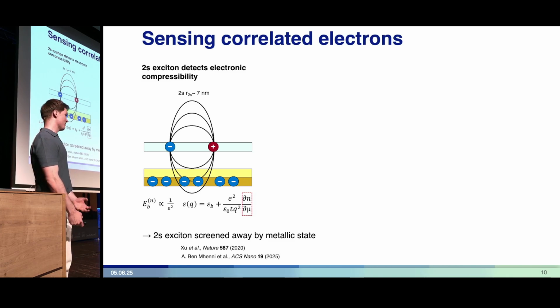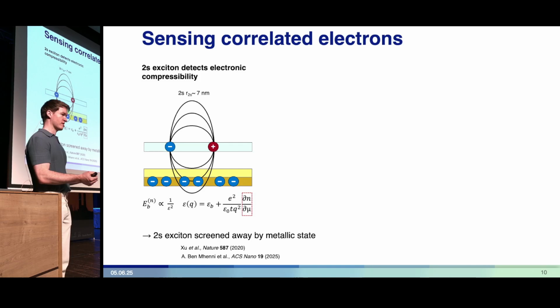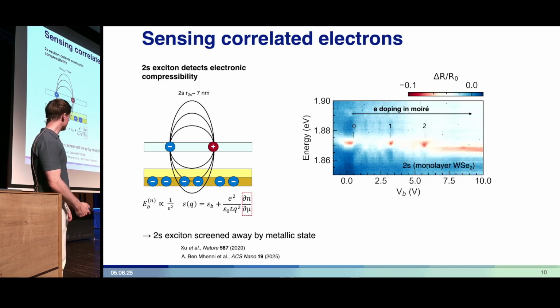This means that when we put charges into the system, if they enter a metallic state, the 2s exciton should be screened away, it should disappear. And if those charges enter an incompressible state, an insulating state, then the 2s exciton should persist. And that's exactly what we see.